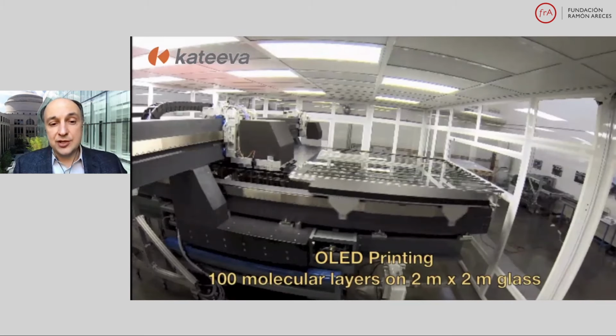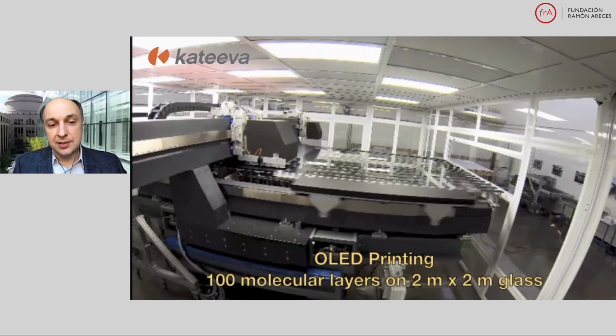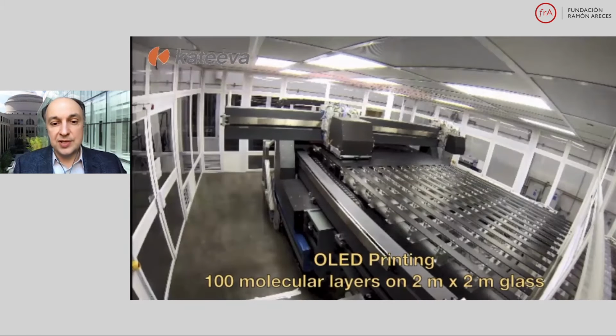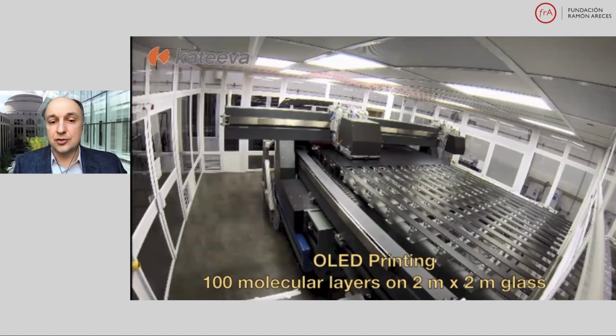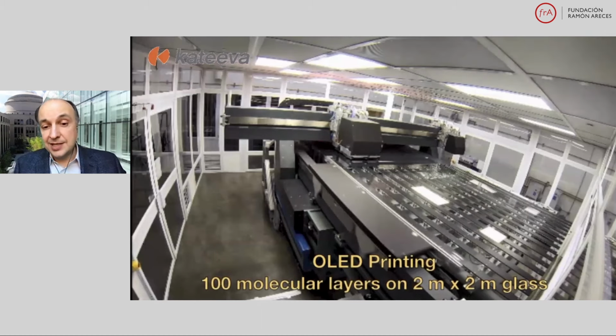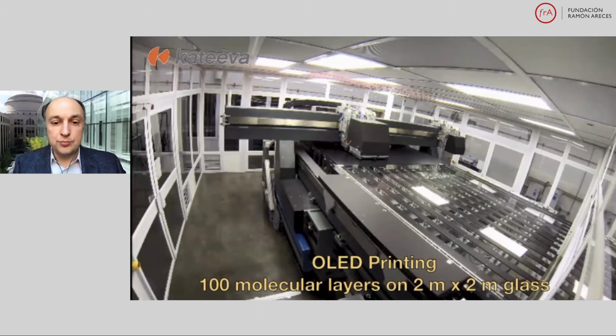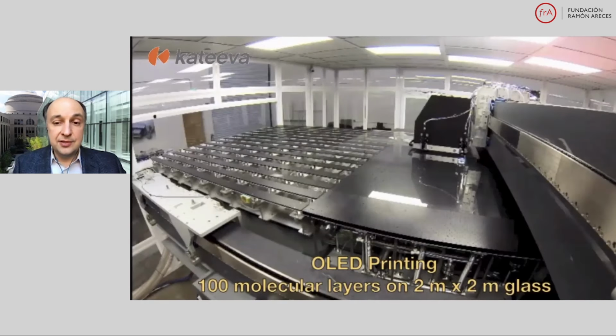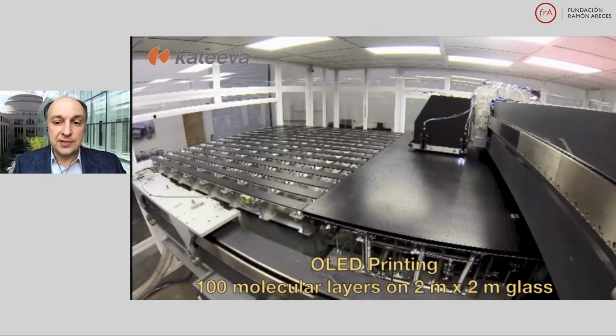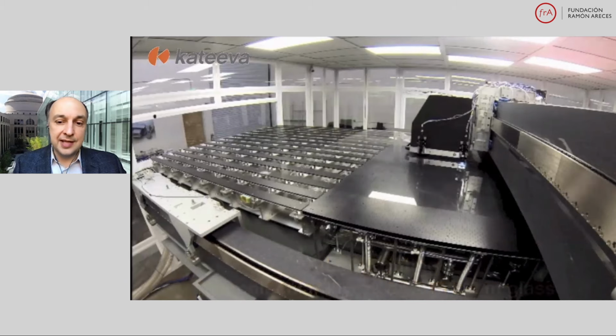Here's a printer in action. It's a 1,000 nozzle printhead that is moving sideways as the piece of glass is slid in the other direction. The piece of glass can be, in this case, 2 by 2 meters in size, and the whole printing sequence will take about 90 seconds from the beginning to the end. Actually 75 seconds in this particular version, because we wanted to leave 15 seconds to dry our printed structure.